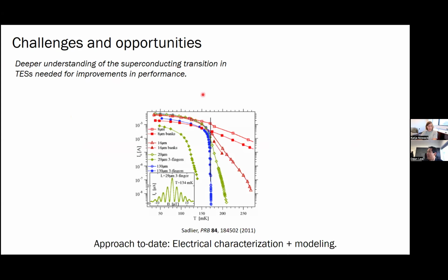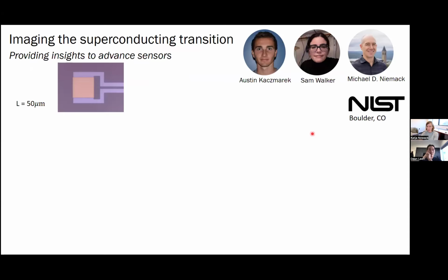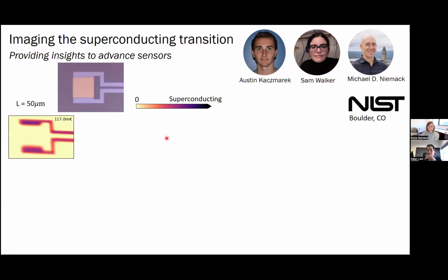And the approach to date to understand the superconducting transition is just a lot of electrical characterization. So you measure a lot of them, and then you do modeling. And it turns out that with our imaging technique, we can actually directly, locally see what's going on in these devices. So that's nice. So here's again the devices that I just explained. And now I'm just showing you images that are taken with our imaging technique of how this device actually goes superconducting. So at relatively high temperature, which is 100 millikelvin above absolute zero. So here I call this high temperature.